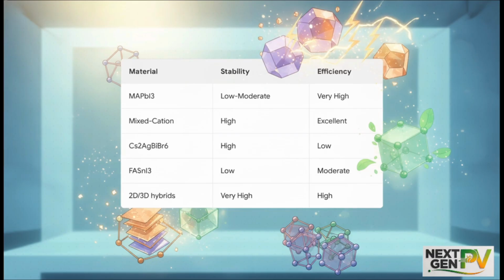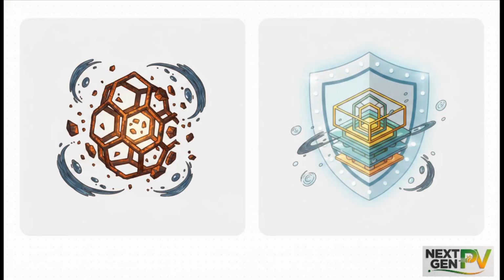Materials like the double perovskite have a great environmental profile, sure, but unfortunately they suffer from a poor band gap and just really low efficiency. Tin is the most direct replacement for lead, and it actually has a beautifully optimized band gap. But tin is a nightmare to work with. It oxidizes instantly in the environment, causing catastrophic degradation.